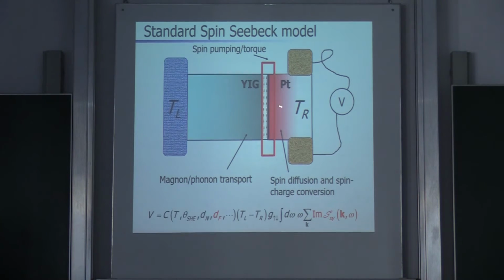Furthermore, usually this one here is an atomistic process, which is not strongly temperature dependent or magnetic field dependent. So in many experiments, you can basically forget about what's happening on the right side and interpret the spin Hall voltages as a function of some parameter as something which has happened in the bulk.